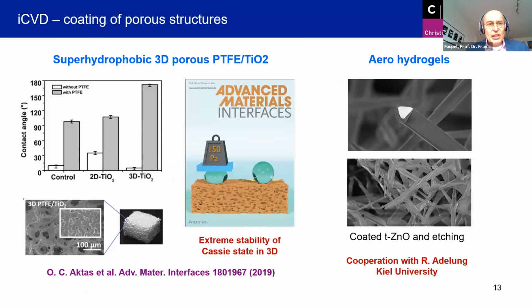In addition to those electret materials, we use the iCVD films also for surface coatings, functional surface coatings. One recent example are superhydrophobic coatings. This is not so special. Many people develop superhydrophobic coatings. Our coatings were designed for extreme stability towards high pressure. So these are 3D superhydrophobic materials where we use the conformal deposition in iCVD to coat porous materials and to get these 3D materials with extreme stability of the Cassie state in 3 dimensions.